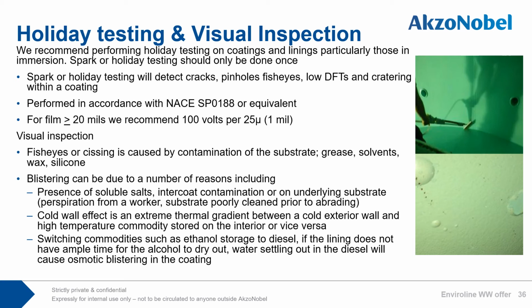Or switching commodities, such as ethanol storage to diesel. If the lining does not have ample time for the alcohol to dry out, water settling out in the diesel will cause osmotic blistering in the coating.